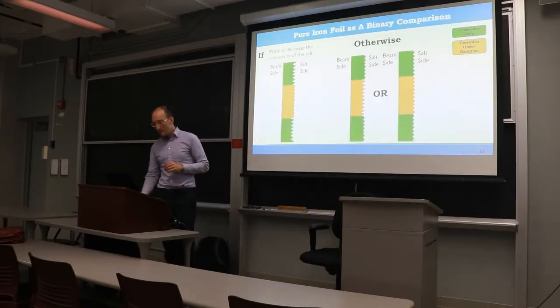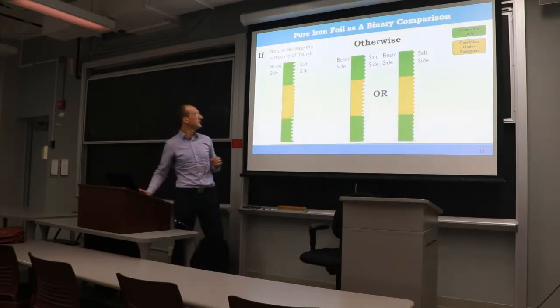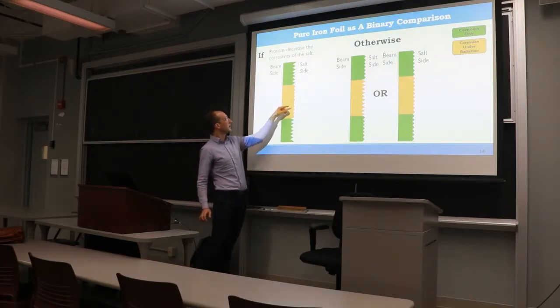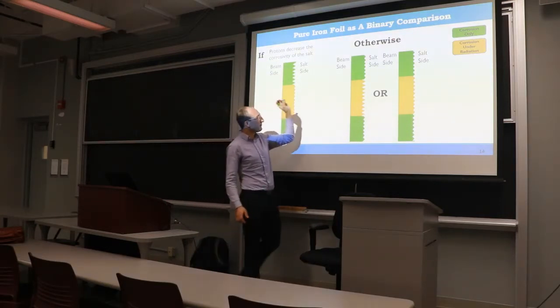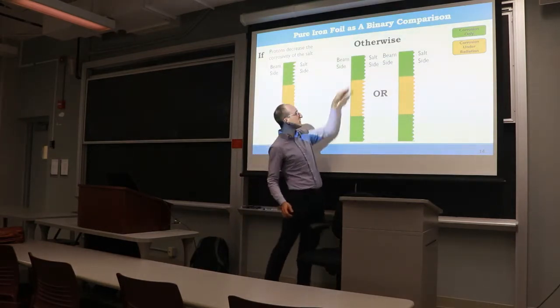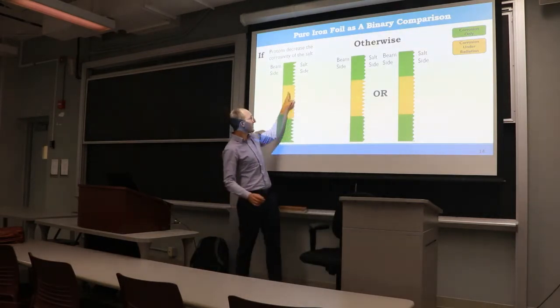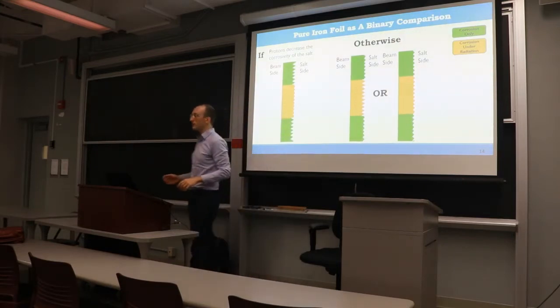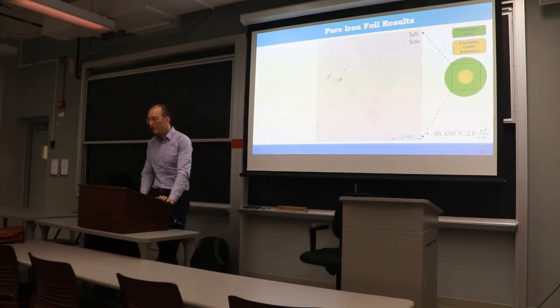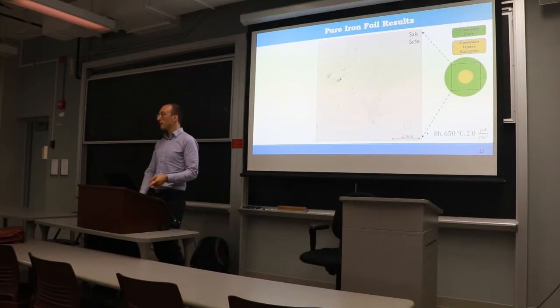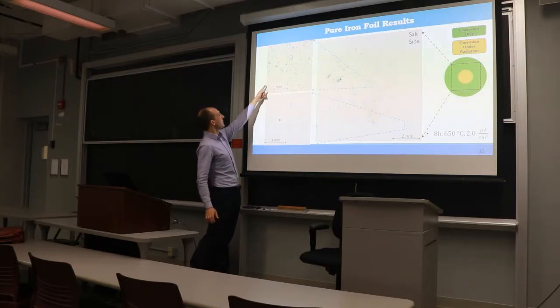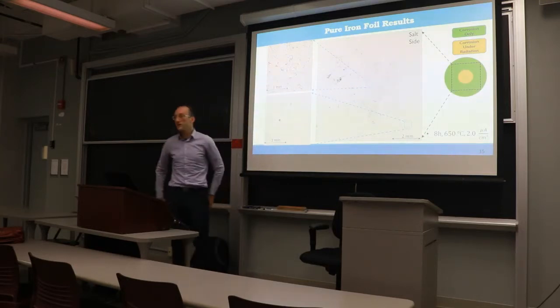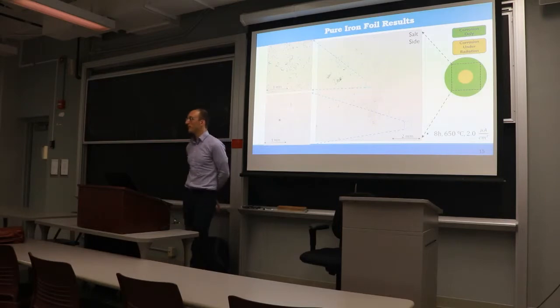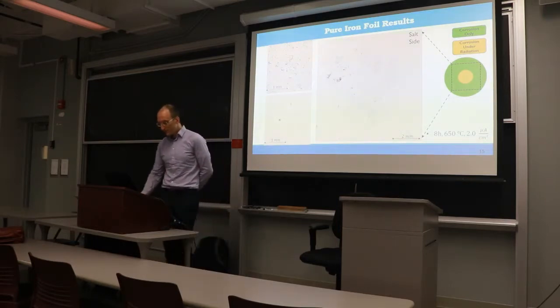By our hypothesis, if protons decreased salt corrosion, then we should actually end up getting the same sort of thing. Or if radiation actually accelerated corrosion, then the regions should switch. The jaggedness of the bars here represents the corrosion depth. And so what we saw is we had a big corrosion spot in the center. When you look at spots in the center where the radiation was and on the outside where the radiation wasn't, you see that the center got intergranularly corroded to hell while the non-irradiated part looks kind of like a textbook picture of iron. And so the region switched position, which is awesome.